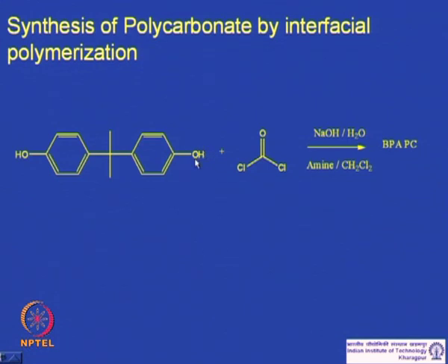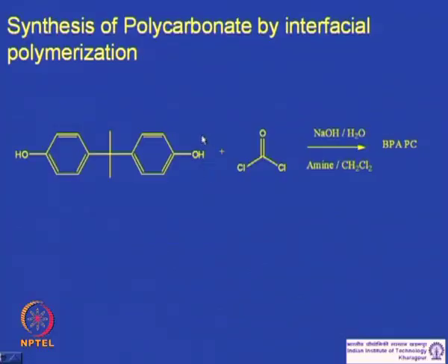Unlike the earlier case, say butylene glycol and ethylene glycol, even if there were differences in the reactivity between the two hydroxy groups, ultimately, even if they make blocky copolymers at the beginning, by reshuffling you would finally land up in a random copolymer. But in this case, the nature of the copolymer would depend upon the reactivity of the functional group.